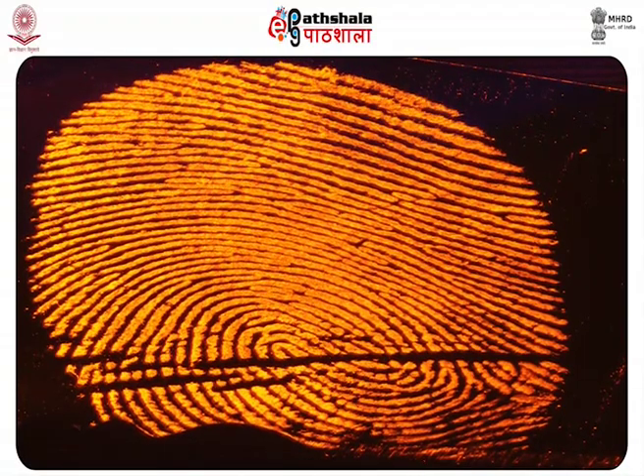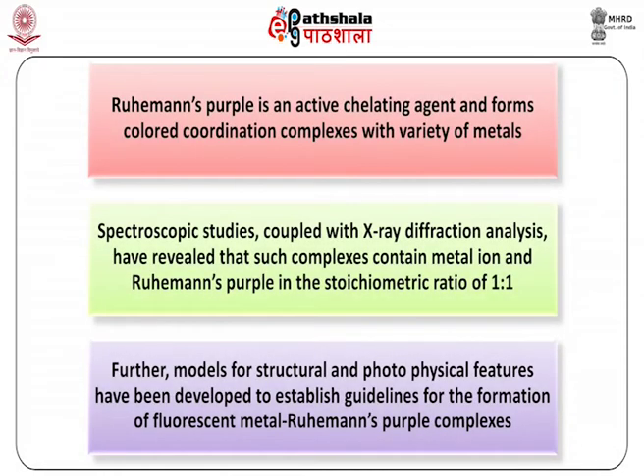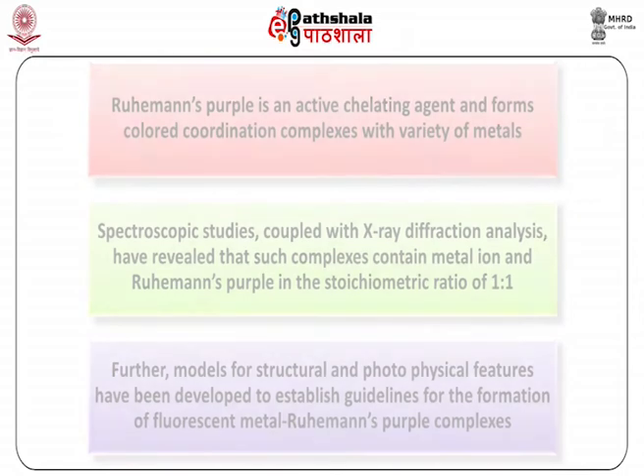The intensity of photoluminescence increases at low temperature. Ruhemann's purple is an active chelating agent and forms colored coordination complexes with a variety of metals. Spectroscopic studies coupled with X-ray diffraction analysis have revealed that such complexes contain metal ion and Ruhemann's purple in the stoichiometric ratio of 1:1. Further models of structural and photophysical features have been developed to establish guidelines for the formation of fluorescent metal Ruhemann's purple complex.